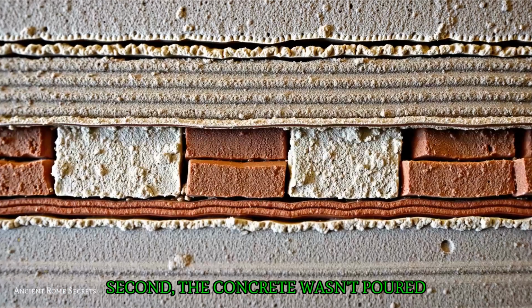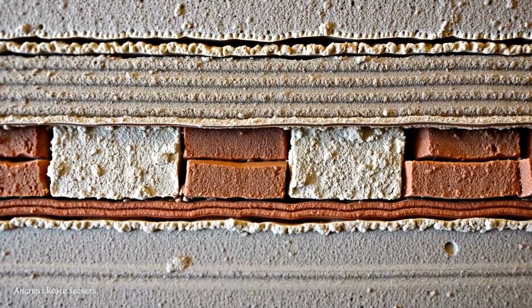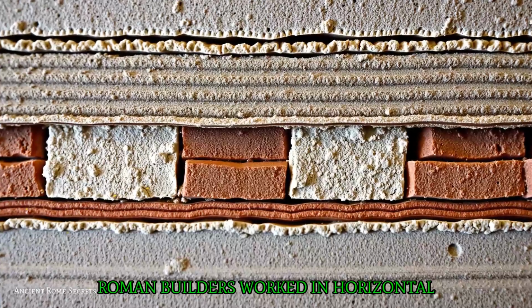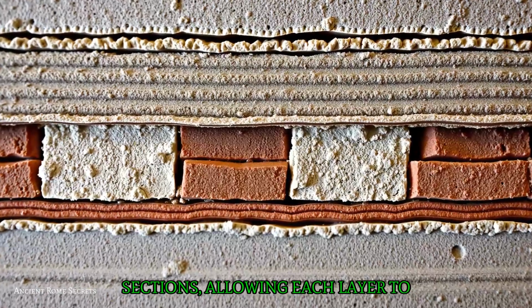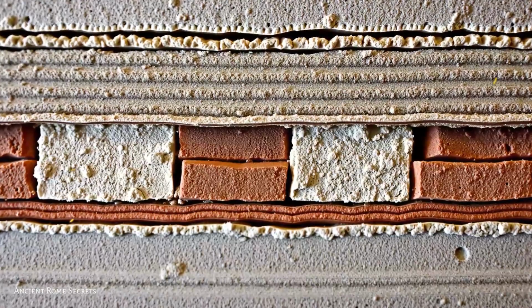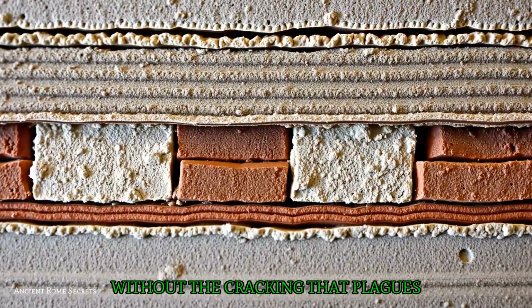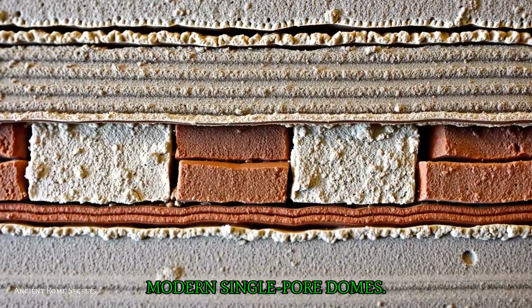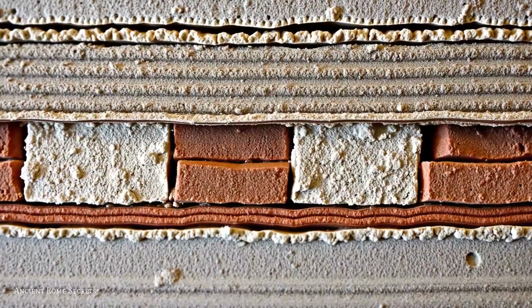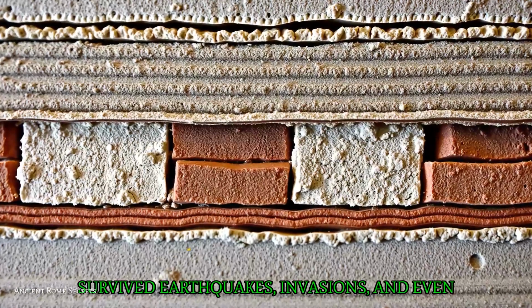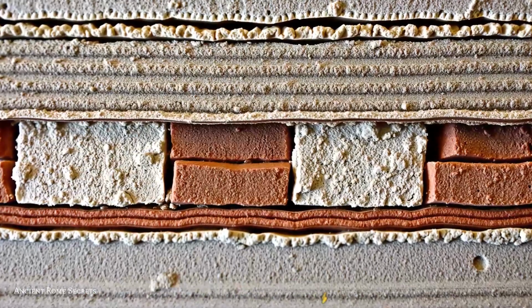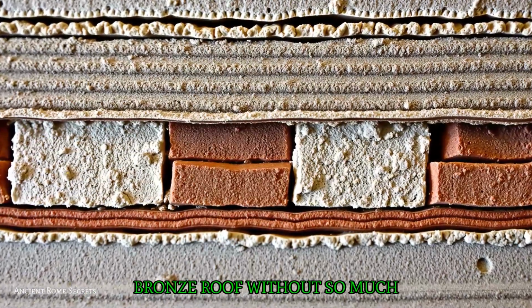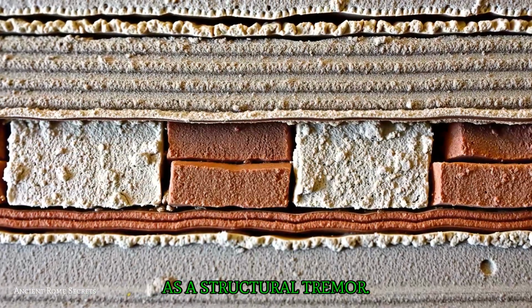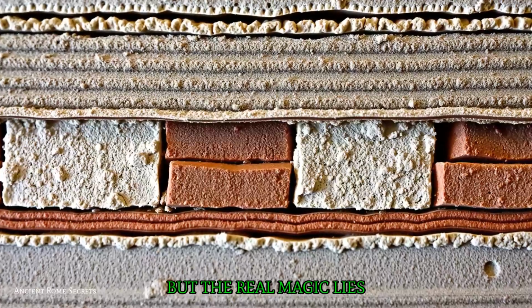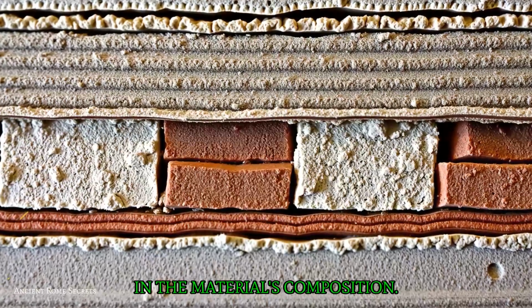Second, the concrete wasn't poured all at once. Roman builders worked in horizontal sections, allowing each layer to partially set before adding the next. This created a monolithic structure without the cracking that plagues modern single-pour domes. The result, a building that survived earthquakes, invasions, and even the removal of its original bronze roof without so much as a structural tremor. But the real magic lies in the material's composition.